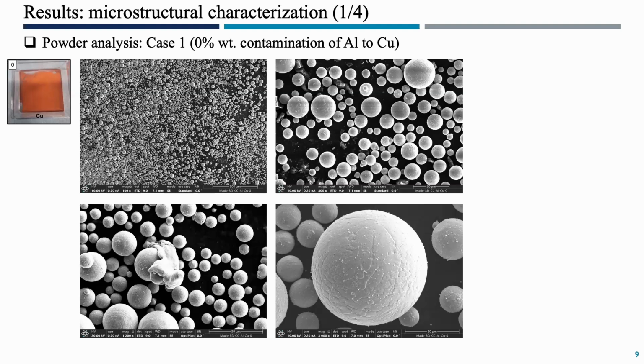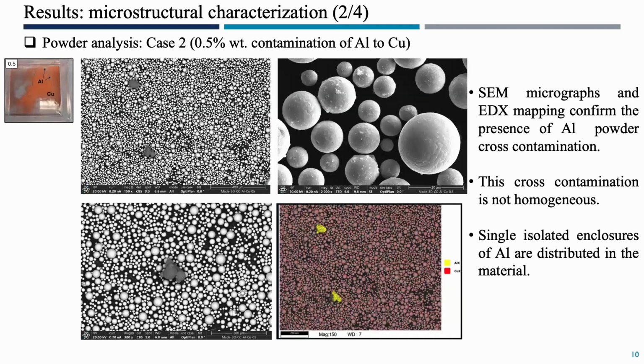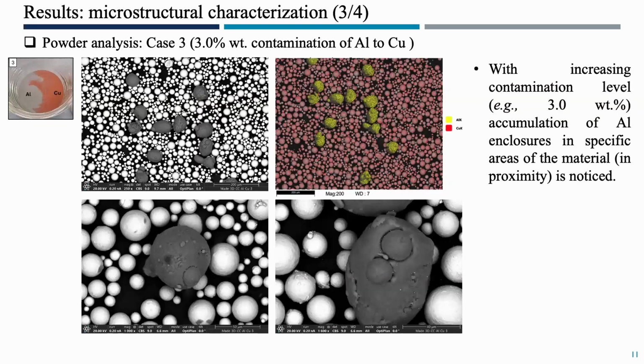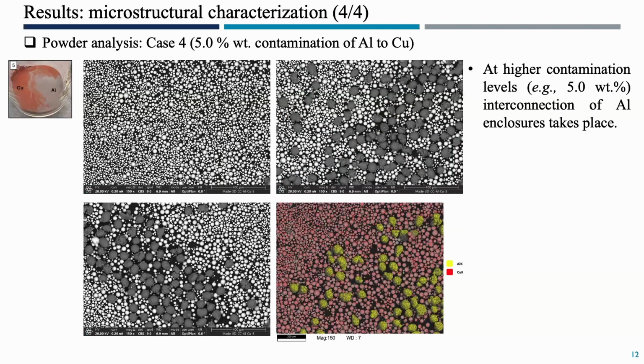from the SEM, showing that, for example, this is the powder at higher magnification of aluminum. Okay, this is of copper. In case that we have 0.5% contamination of aluminum, then you can see one or two aluminum powders in the samples, then it's much more evident. With higher contamination, you can see the powder of aluminum has higher dimensions than the diameter of the copper powder. And of course, at higher contamination, for example, 5%, then you have something like interconnection between the aluminum particles.